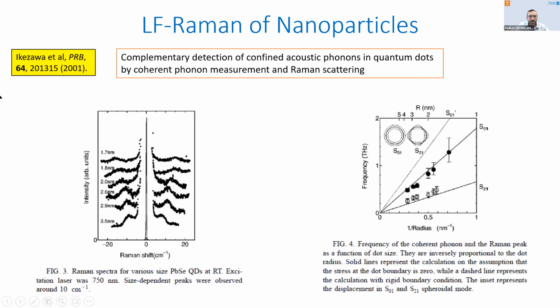Here's an example from a few years ago, 20 years ago actually, where this group was looking at quantum dots. And looking at the low frequency Raman, you could see that there are changes in the low frequency Raman depending on the size of the dot. As the dot becomes smaller, the Raman scattering gets larger. So this is very exciting for metrology, right? Because Raman, and especially low frequency Raman, becomes more sensitive as your structures get smaller.